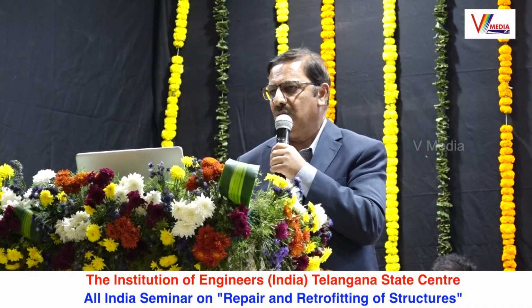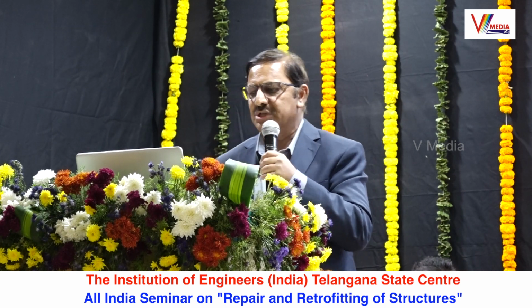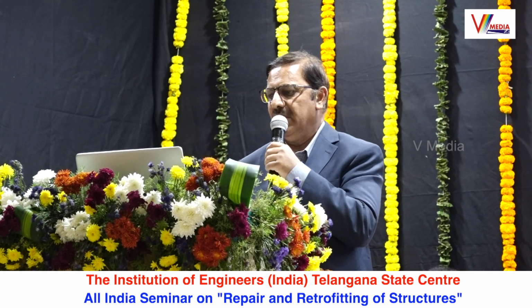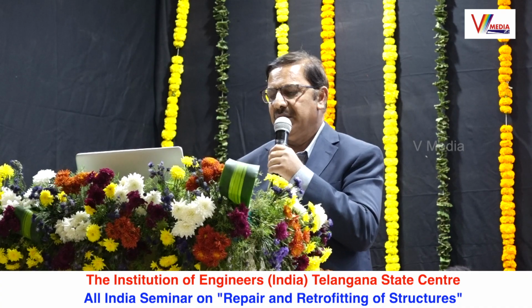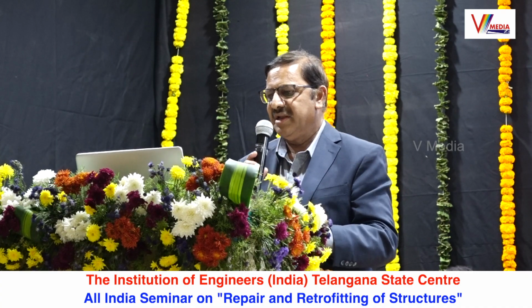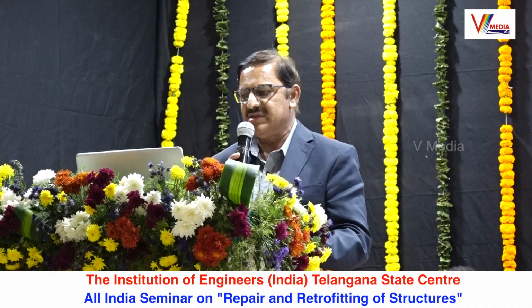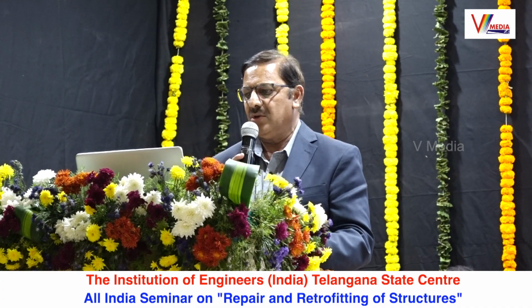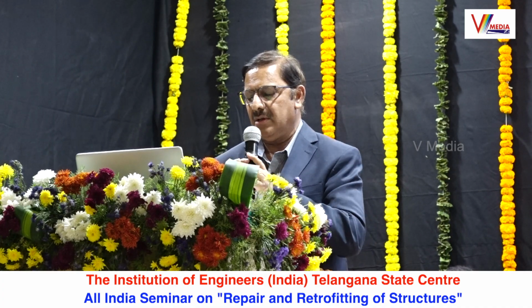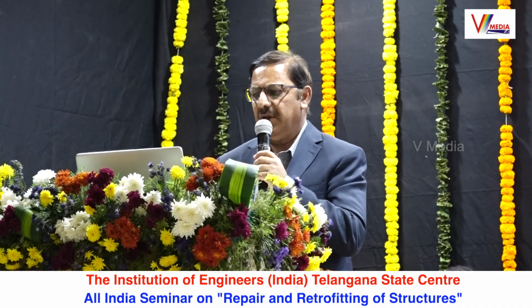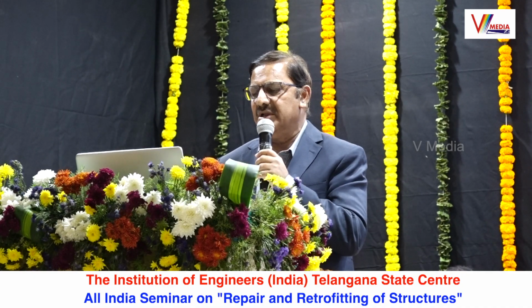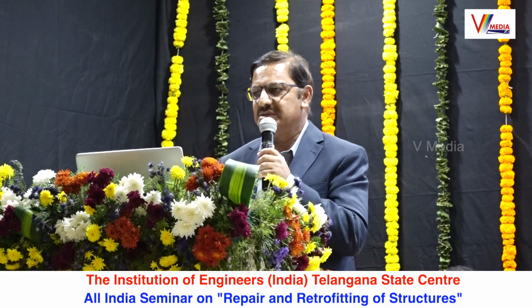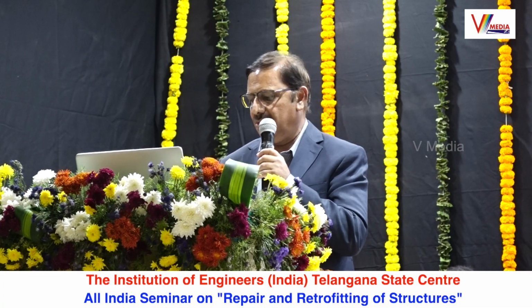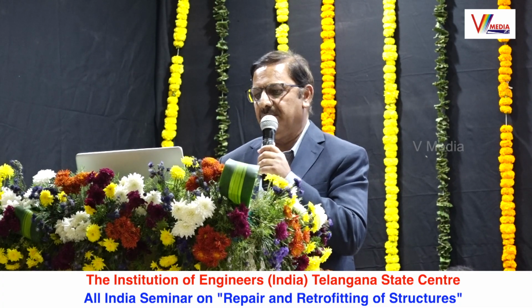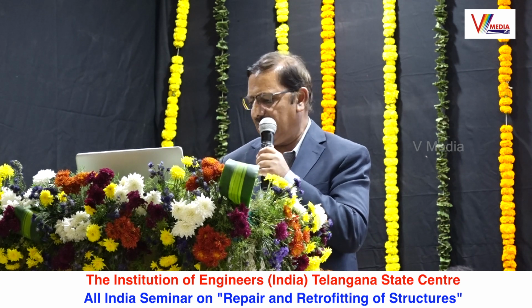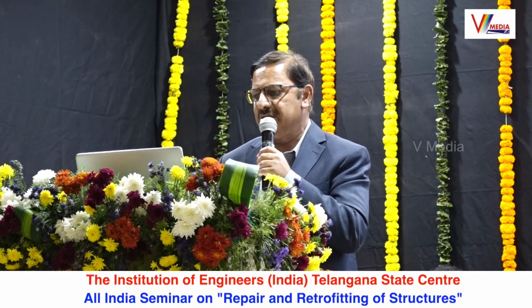And the impressed current anode is used mostly in industries and is more commonly used than the sacrificial anode. It is used for large structures, and it has a longer life expectancy. You can design the life actually. Concrete with any chloride level can be protected using impressed current as well as sacrificial. It meets varying current demand. If your current demand increases, like you want to connect more structures to your system, you can increase the number of anodes and increase the current capacity. The disadvantage is high cost, because it is a high-end material, and regular maintenance is required.